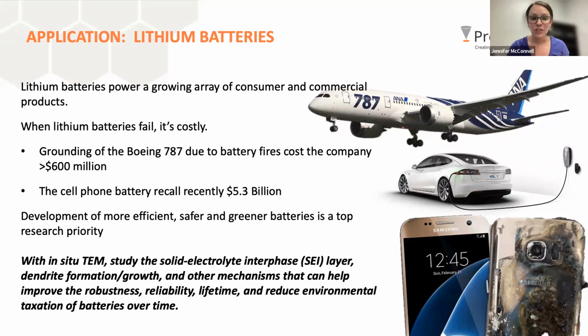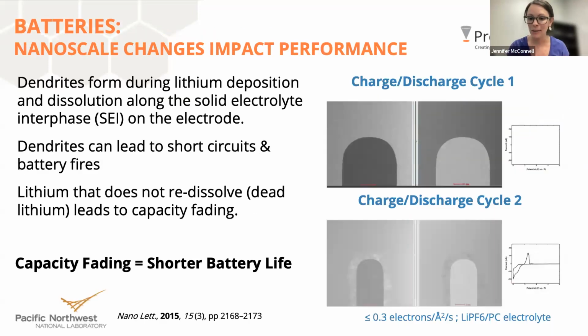And so with in situ TEM, you can study things like the solid electrolyte interface layer. You can understand dendrite formation and growth that's occurring during these charge-discharge cycles, and other mechanisms that help you understand failure, which can then help you improve the robustness and reliability and lifetime of the battery, and reduce the environmental taxation of the materials over time. And you can't get to that resolution or that type of information with any other technique. So let's look at some examples.